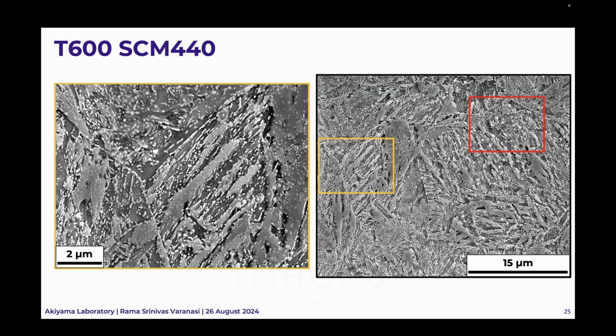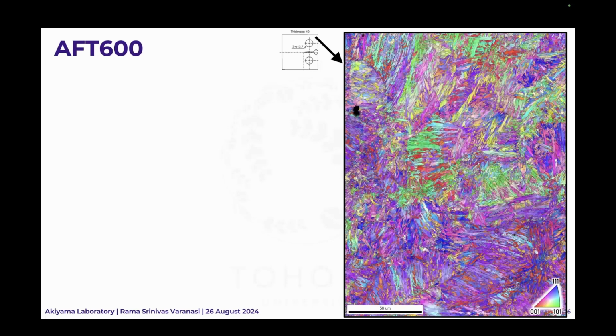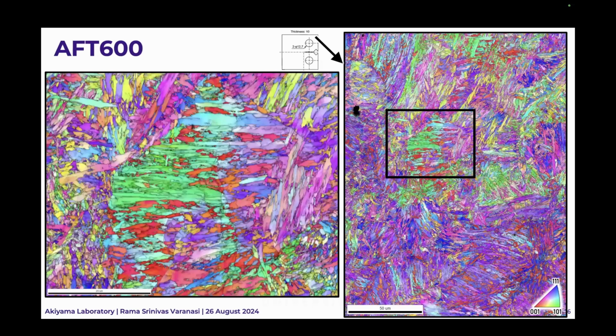Now, the question is, why is this important? We'll come to it in a couple of slides. But now when we look at AFT600, we looked at this corner where it does not have any influence from this crack propagation. So we consider this as the undeformed state. We can clearly see that we have this nice prior austenite grain boundary.